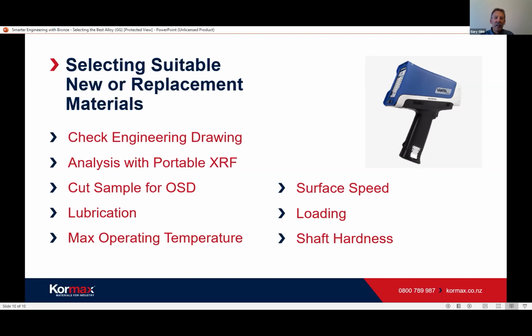If that's not possible, then you can analyze it with a portable XRF machine that analyzes the chemical composition. That's the little machine on the right there. That zaps it with X-rays for anything from 10 to 25 seconds and gives you a breakdown of the chemical composition of the bush. Now those guns will do copper alloys, aluminium, steels, a multitude of different alloys. So once you've done that, you can often fit it back to a standard or something like that.